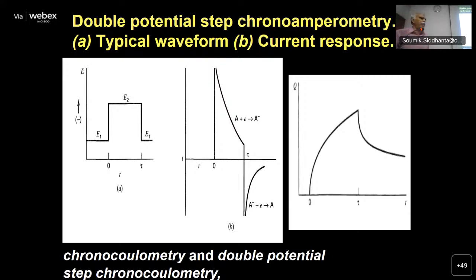Imagine anthracene in deoxygenated DMF. Deoxygenated because we want to remove all oxygen. We don't want oxygen reduction. So anthracene is put, and let us say anthracene can become anthracene radical cation, and when I reverse it, the radical cation can get consumed. So please look at the second plot. Current as per the Cottrell equation shows a decay, and then all of a sudden I am changing the potential to the final value. I'll see a reverse decay. So this shows a typical reversible pattern of a double potential step.